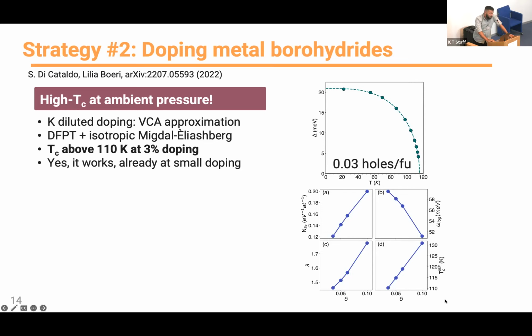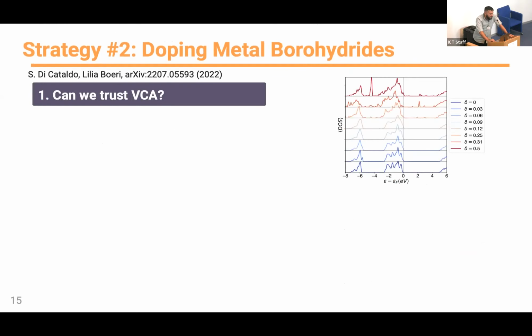Now, what's remarkable is that if we were to extrapolate this to lower dopings, we would still have a high TC even at smaller doping values. Now, a lot of our efforts after we did this calculation was placed into trying to be as confident as possible that the approximations that we made were reliable, because we understood that people could be skeptical about this. So we try to answer the questions: can we trust the VCA that we use? And can this system be realized in experiment?